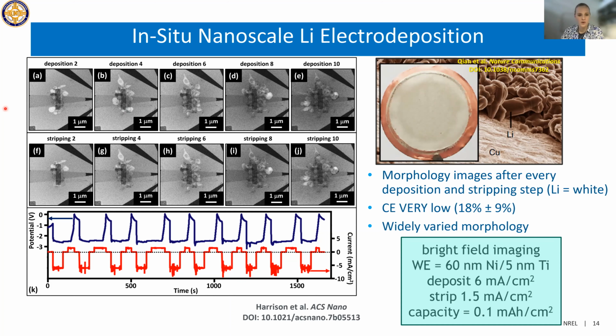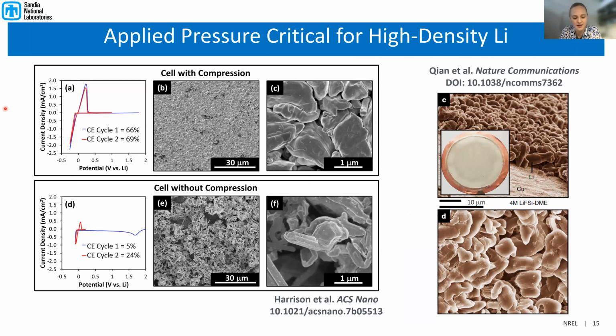And so what we understood was that the layout of that TEM liquid cell was very different from what was being done in the coin cell, because there was no contact pressure on the electrode surface. And so we demonstrated that here with a coin cell with compression, where it had fairly good coulombic efficiency, and we're seeing these nice big lithium grains, compared to a cell without compression, so just an electrode in a beaker, where you have this very open, mossy lithium morphology. And so the environment around the lithium makes a big difference on the resulting lithium morphology.